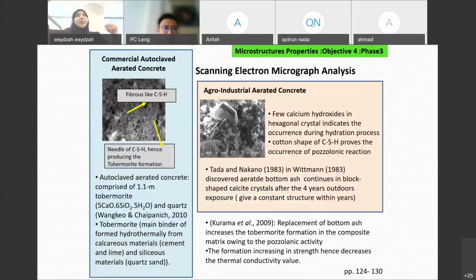Okay. If you can still remember, just now I did mention aerated concrete, whereby the aerated concrete produces ettringite. So ettringite is the one that creates the strength. And again, if you can see aerated concrete here, this is what I call ettringite. If we look here, it is like a needle shape. This ettringite will produce what we call tobermorite formation, and tobermorite formation is what creates strength in the structure. Okay, this is normal commercial, and I compared it with the one that I did, and I can see that my material is slightly different, whereby it created a hexagonal crystal. This hexagonal crystal is actually calcium silicate in a hydration process, and we can see a cotton shape. This cotton shape is actually calcium silicate hydrate gel, which will cause a pozzolanic reaction later on.